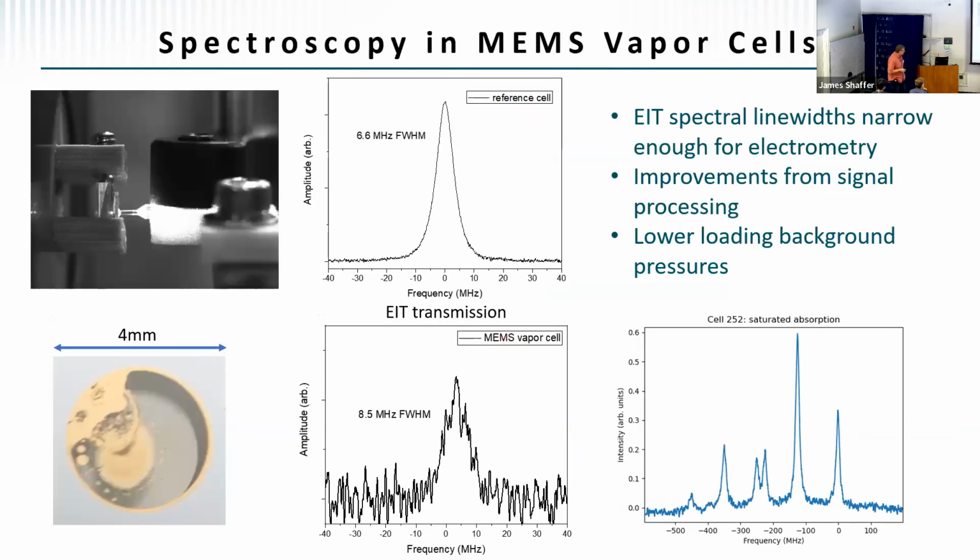And this just shows some other technical things about filling the cells. It's quite challenging to actually make these cells so that we don't have charges that build up on the walls. So again, that's some material science, but we're able to cut the walls to within about 15 microns of accuracy, and we usually can get the surface roughness down to several microns in a straightforward manner by treating them with some chemicals.